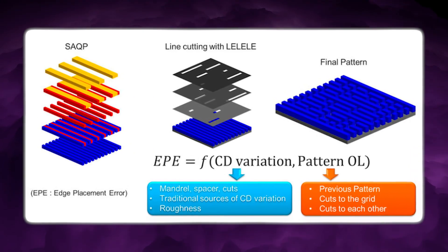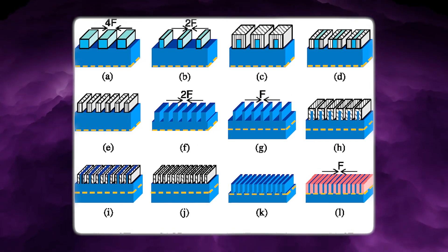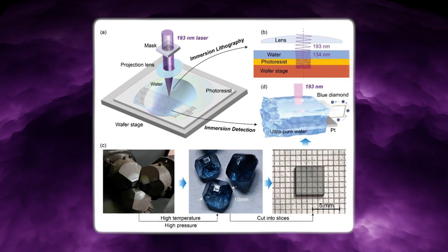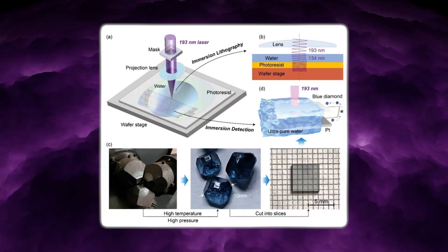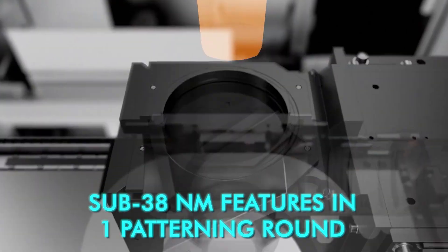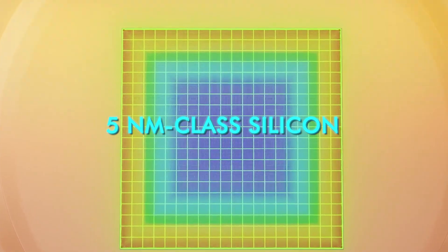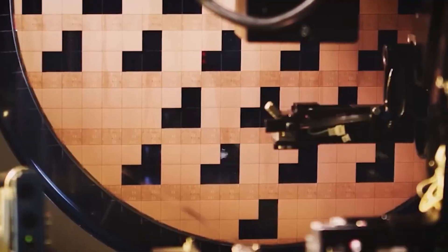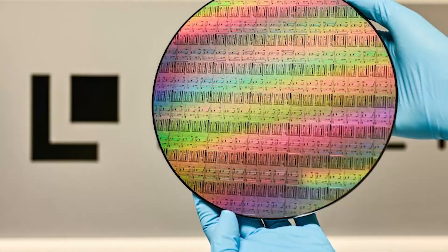The Kirin 9030 is not printed with EUV. It is printed entirely through DUV immersion with multi-patterning techniques like SAQP — self-aligned quadruple patterning — which has been a known method in chip making for years. SMIC likely optimized its 193 nanometer immersion scanners to push near 35 nanometer resolution per single pass, then applied multiple rounds of aligned exposures to etch dense metal and transistor layers. The best commercial DUV immersion scanners can print sub-38 nanometer features in one patterning round. That means 5 nanometer class silicon is theoretically possible with DUV, but every generation smaller requires exponentially more printing passes, tighter metal wiring pitch, and more defect opportunities.